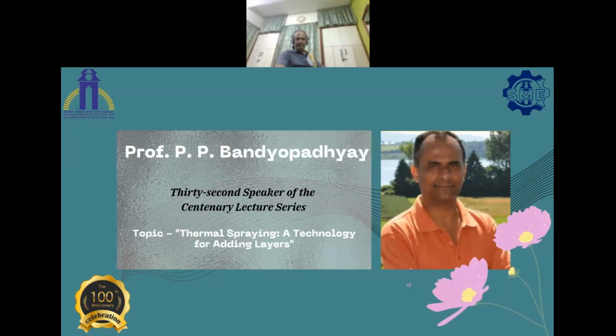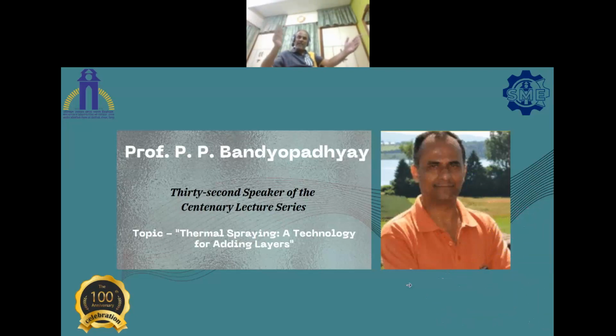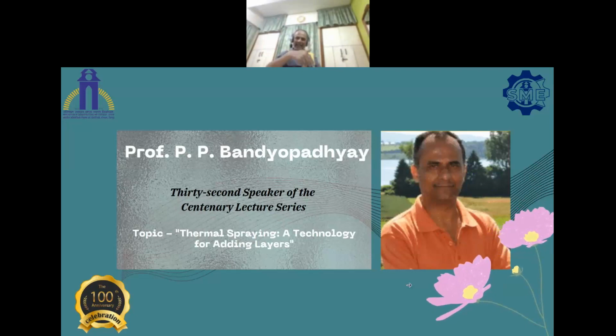Let it just happen something like this. Initially, you have a cold layer. On top of it, you have a hot layer. The cold layer is also not very cold, so to say. So together they expand. Problem starts when cooling occurs. The metallic substrate has a thermal expansion coefficient. The ceramic or another metal has another thermal expansion coefficient. They contract differently when they come to room temperature from different average temperatures. It may so happen that the substrate during cooling is compressing the coating, making it compressive, or the substrate does not contract to the extent the coating would like to, leaving it in tensile mode. So it is the differential thermal expansion that dominates the scenario.